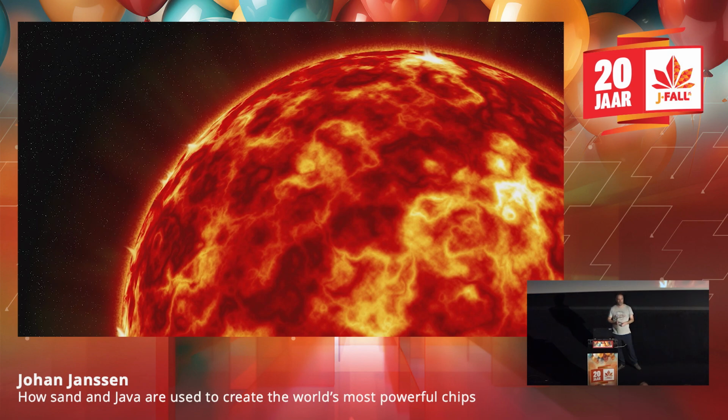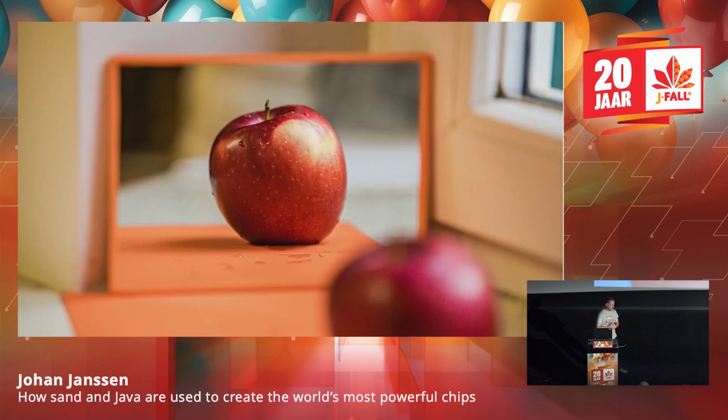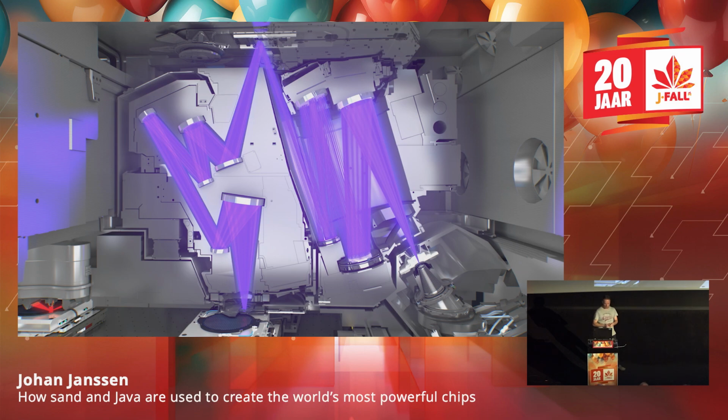Our current newest machines use EUV light, which is quite a brittle light. It goes away quickly, so we need to take a lot of precautions to make sure it still exists and doesn't vanish. For that we use mirrors. These are some of the flattest mirrors you can find. They have about 100 layers of special material. If you were to stretch one to the size of Germany, the highest bump would be 1 millimeter. So they're really flat. And that's then put in the machine.